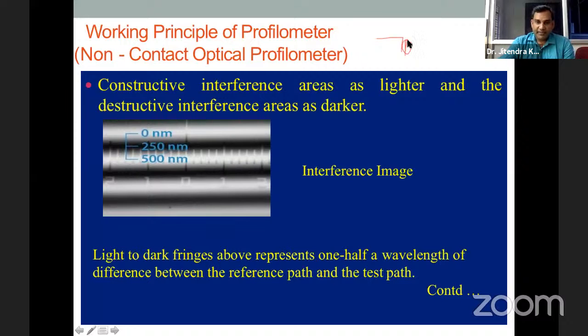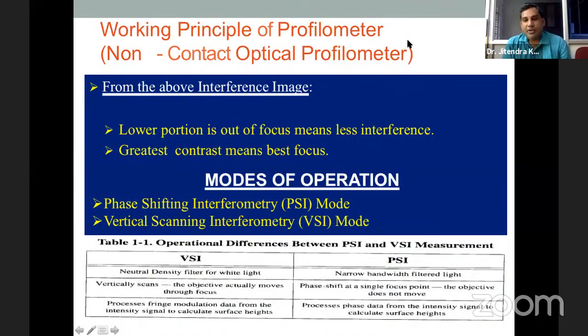This 3D optical profilometer works in two modes: one is phase shift interferometry mode, PSI, and the other is vertical scanning interferometry mode, VSI. VSI mode is generally used if your surface roughness is in microns and you can observe it with the naked eye, where the roughness is somewhat higher. But when you have a very smooth surface, then PSI mode is used, and PSI mode gives more accurate results than VSI mode. So this is the only difference between these two modes.